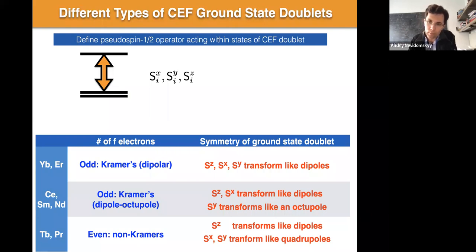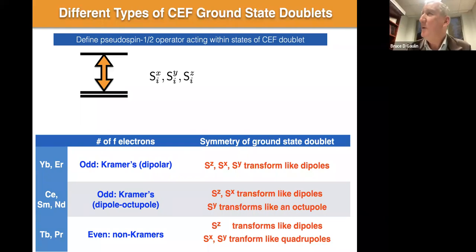Now, I'm not here to defend Roman, but I'm curious, what is your take on this? Do you believe it's the way the crystals were grown, or do you believe this could indeed be which machine you measured the signal on? Yeah, so I'd say there's two points. One is that I do think that our crystals are likely better than their crystals, but that's simply because they were grown at lower temperatures, right? If you grow at lower temperatures, you don't introduce the same sort of defects. That's true even if you use the same technique and grow at two different temperatures. The lower one is usually the one that will have fewer defects. And here the temperatures are a lot different actually, because in one case it's hydrothermal, and the other case it's solid state synthesis. You're close to the melting temperature, for powders.